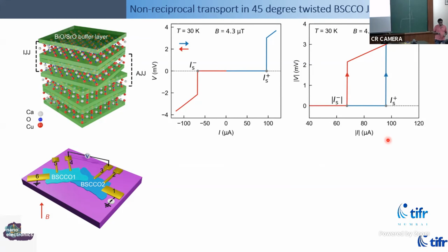So we are using Scotch tape to peel it out and then rotate it and fix it like that. It's analog, or another name, it's a PDMS. It's a sticky polymer. We take a crystal, put that sticky polymer on top of the crystal and cool it down to the temperature I mentioned, something like minus 100 C. And then we pull it out. And that polymer grabs and picks out a set of layers inside the cryogenic state. Then we rotate it by the angle we want and put it back.